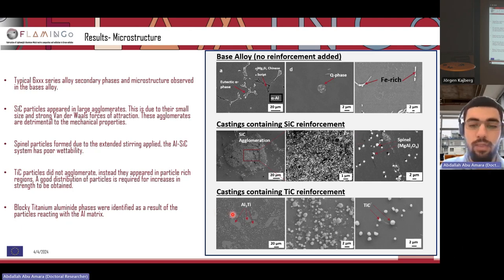And as for the castings containing titanium carbide, luckily we didn't see any particle agglomerations. The particles tended to appear in these particle-rich regions, but they weren't agglomerated. We can actually identify the individual particles freely present in the matrix. So this was a much better distribution than the silicon carbide particles. We also saw, quite interestingly, these large blocky titanium aluminide phases, or Al3Ti. And the reason for this phase forming is because of a reaction between the titanium carbide and the aluminium matrix.